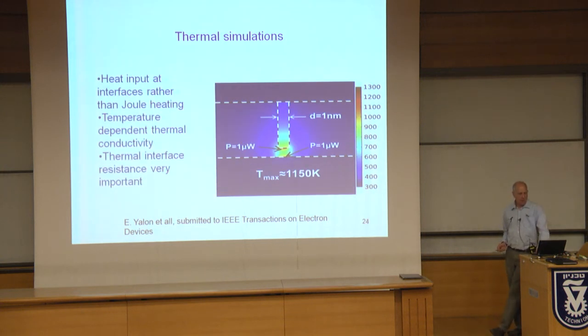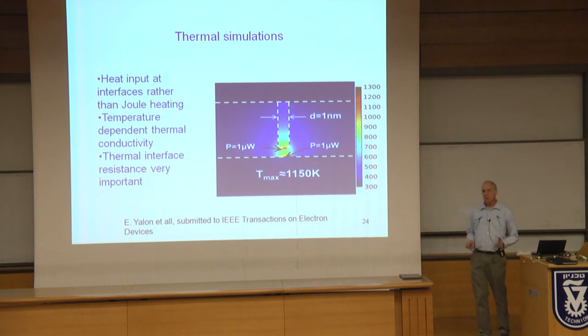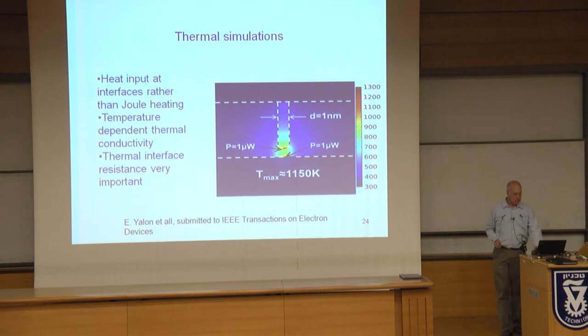Some of the issues are: where is the heat input? In our case, heat input is at the interfaces because most of the voltage is applied across the tunneling gap. So we actually have no Joule heating of the filament, or mostly heating at the interfaces, bottom and top interfaces. So this was our heat input in the simulations. There is some temperature dependence of the thermal conductivity, which is not well known, and a very important part, which I think is recognized by most groups working on thermal simulations, is that in nanometric dimensions, the thermal interface resistance is very important, actually determining the temperature rather than the bulk properties of the material.